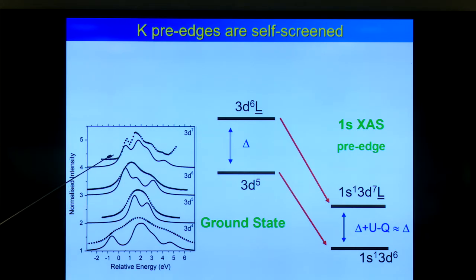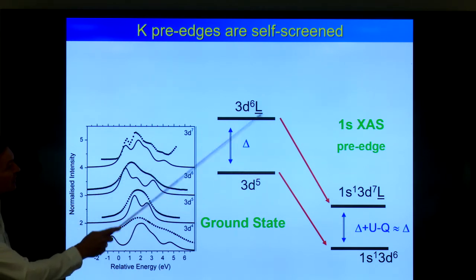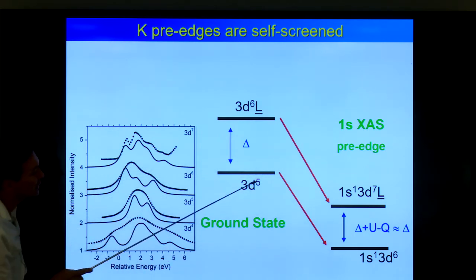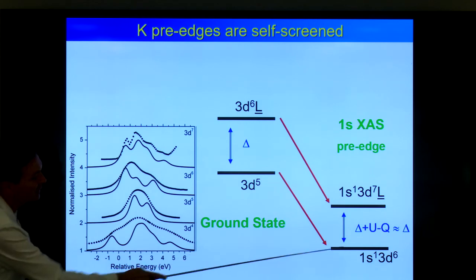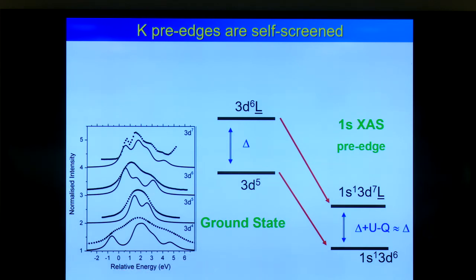People working in the hard X-ray range realize that this is not a normal pre-edge, because then you will not see this fine detail. This is a high energy resolution fluorescence detected spectrum where you can see all the fine details of your pre-edge, and then you can compare that with the multiplet calculation. Again, you can do the multiplet calculation because it's a self-screened process, and you can, in first approximation, do d5 to 1s1 3d6, and that works. Now to the edge.